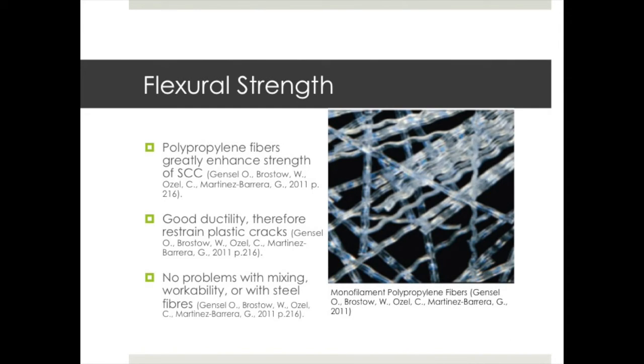Polypropylene fibers have good ductility, which greatly enhances the strength of self-consolidating concrete by restraining any plastic cracks. There is no problem with the mixing or workability of the concrete when the fibers are added. The polypropylene fibers also don't cause any problems associated with steel fibers.